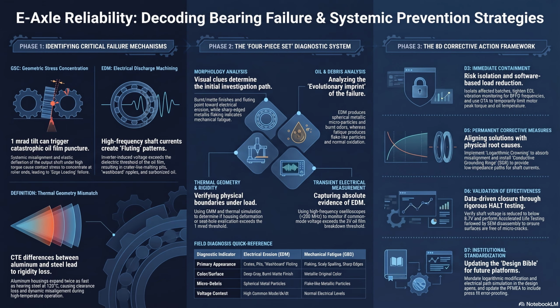Piece number 1 is morphology, the visual evidence. They put the damaged bearing under a scanning electron microscope, an SEM. And electrical erosion leaves a very specific signature. To the naked eye, it looks like a gray matte finish that turns into washboard-like fluting, like the grooves on a vinyl record, perfectly spaced apart. And under the SEM, they see microscopic craters and what's called a white layer.